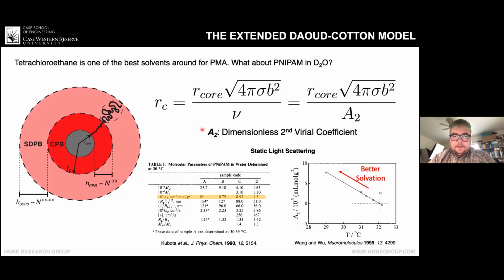Does it expel solvent when it collapses? That's what we were thinking. It would expel solvent and then maybe it can get closer. We didn't see that effect, and there are many reasons why we can't see it. We have issues with neutron scattering going to higher temperatures, because these particles aggregate to a very small extent, and that just destroys the scattering pattern. It makes it very difficult for us to analyze them.